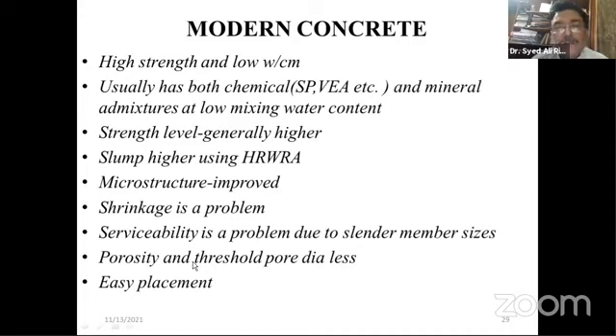In general, if you test a high strength concrete cylinder, it should explode like a cartridge in a shotgun. In a displacement controlled machine, you can also listen to the internal cracking. You will notice that internal phases are cracked while there is no crack on the external surface. But when they explode, they explode very, very strongly.